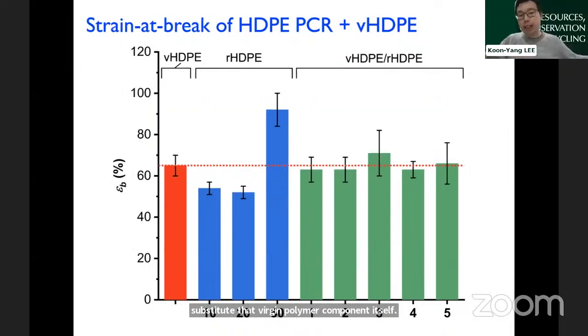We then look at ductility, what we call strain at break. Polyethylene is relatively ductile, with 65% strain at break. Those recycled severely, the 50 times recycled polyethylene, have a very, very high strain at break. Once again, this corresponds to that molecular weight decrease, where the whole thing becomes significantly worse, so the chains can all slide over each other. Blending in virgin polyethylene didn't lead to a significant change in strain at break. Again, that's a good sign that you do need to blend these highly recycled polyethylene with virgin polyethylene to maintain the mechanical performance that you actually want.